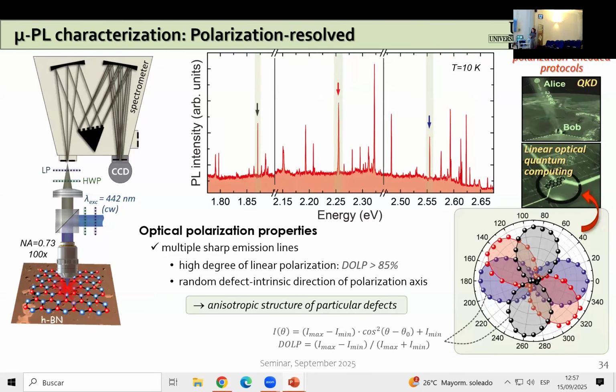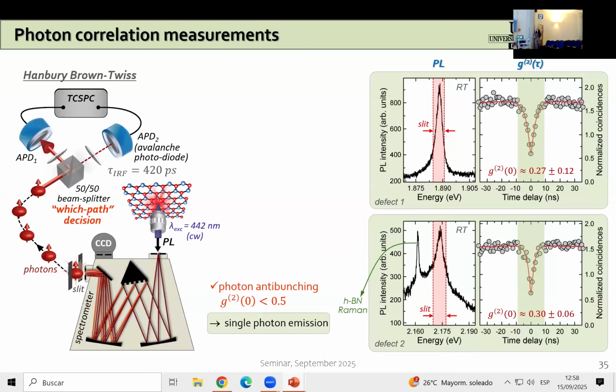So we also wanted to check what is the polarization of these PL lines, because as I mentioned, this is important for polarization encoding protocols. So we randomly chose some of these lines at different energies, and we saw that they indeed are highly linearly polarized with a degree above 85%. The fact that the random defects have actually intrinsic orientation of the polarization axis, as you can see here, suggests that this high degree of linear polarization is due to the anisotropic structure of the particular emitting defect, which actually are electrical dipoles.